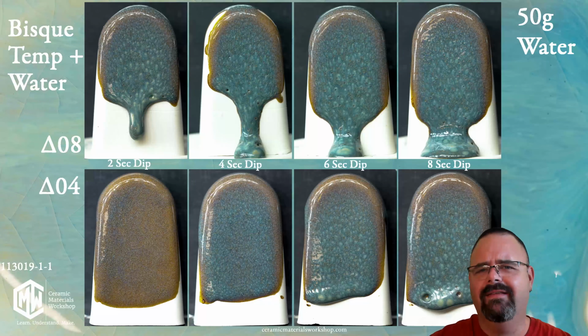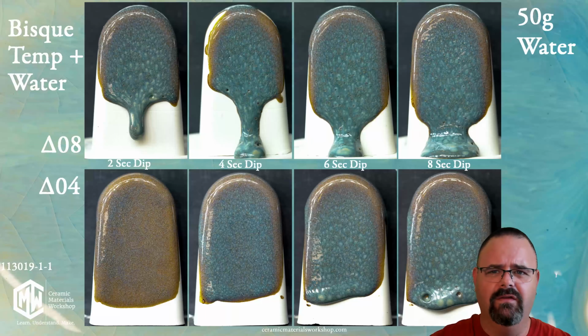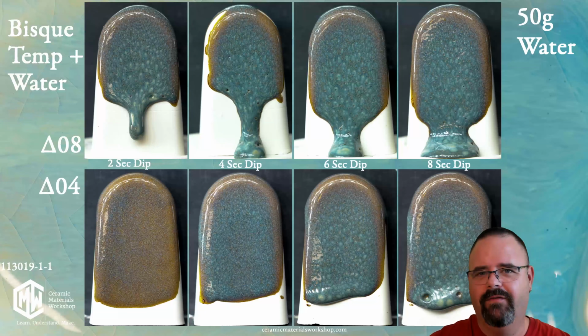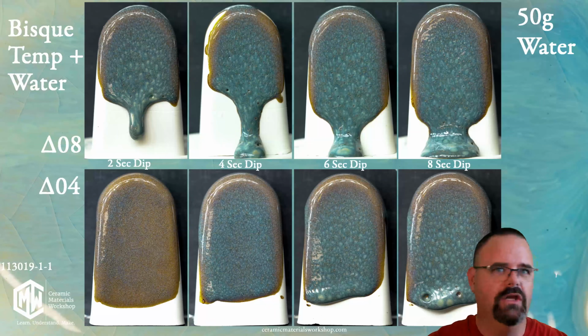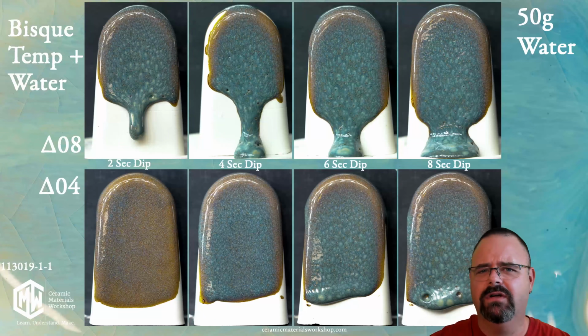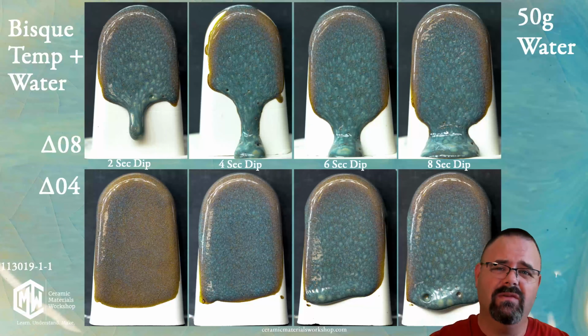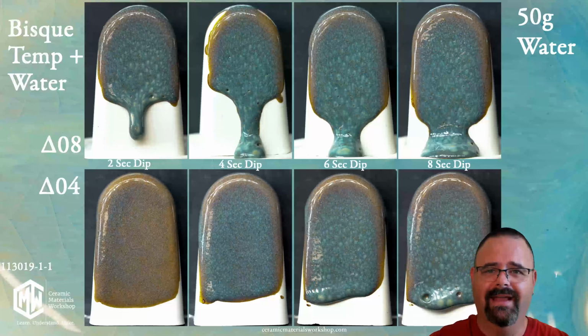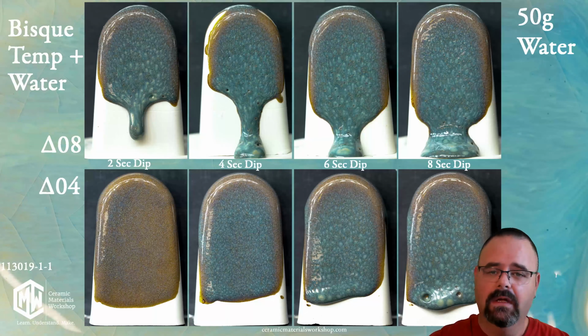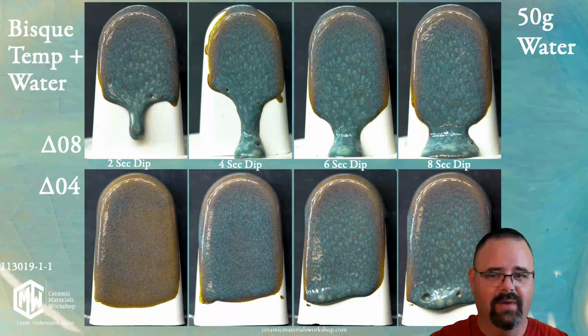Now, I will go off on a side tangent that oftentimes people will say, oh, why did my glaze run when I layered these 2 glazes? You'll often find everybody online jumping in and saying, oh, you've got some magic eutectic reaction where all of a sudden you've created a new lower temperature. No, you didn't. What happened is you just put on two really thick coats of glaze and you didn't really think about it, because we have sort of a distorted view of how thick a glaze application really is. Okay, and it's very easy to put on two really thick coats, especially when you're layering them. So just be aware of that.